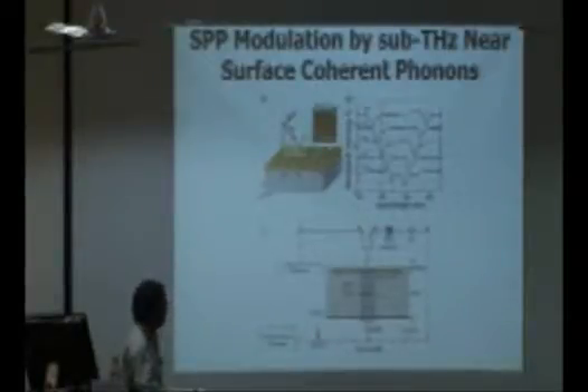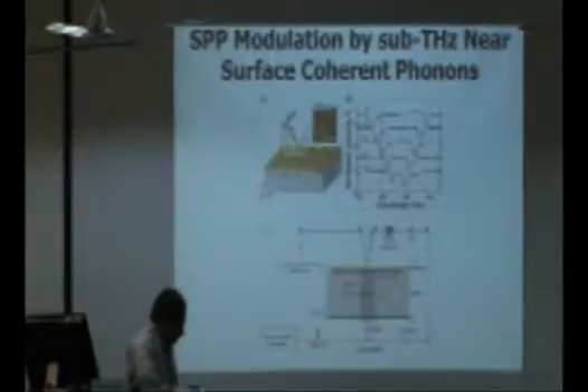So one way is that we put this transducer at the bottom, and then by an incident light pulse we can generate acoustic phonons in the medium. So these acoustic phonons, which are propagating in the direction opposite to the incident light, modulate the incoming light.